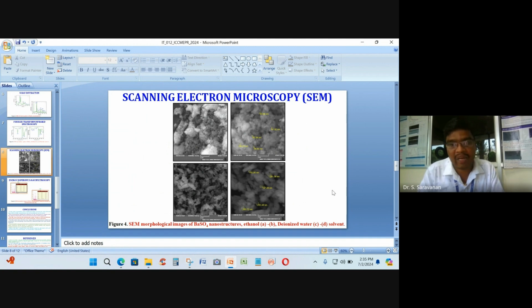Here, this is the scanning electron microscope. You can see that the first two represent the ethanol-based morphological structure, and the second the DI water-based morphological structures. The first two represent the smallest nanostructures. They look like rods, and when we take the average of that size, it comes to around 77 nanometers. However, the below two diagrams represent the water-based nanostructures. It is clearly visible that the agglomerations are very few and they are free. They look like nanorods, and the average we got is around 225 nanometers.